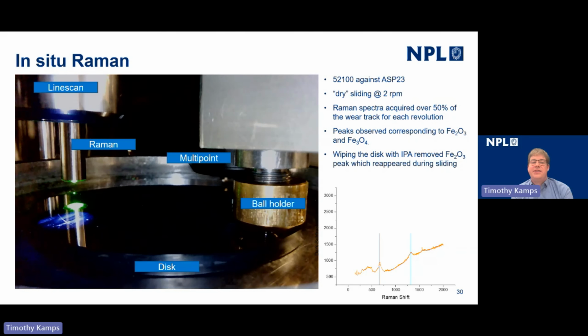We're interested in how fast it takes for the formation of the oxide film and how tenacious that oxide film was. So there's a graph here at the bottom right, and what we can see is successive spectra, and you can see that actually the Fe2O3 peak reappeared after we'd removed it really quite quickly, and then we can see the saturation of that. So this is a measurement capability that we're developing at the moment, understanding how the system works in real time. But there is a clear advantage to being able to identify chemical species during the sliding experiment. And this year, this capability is being developed to work in the presence of lubricant, both the Raman and the vision system, which has been already proven to work in submerged conditions.